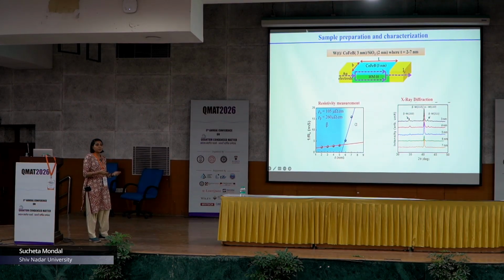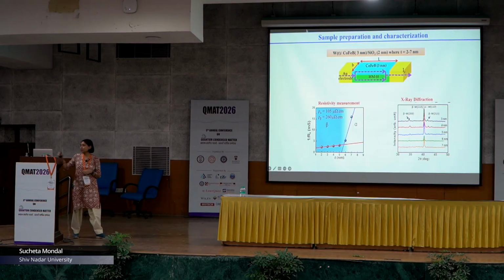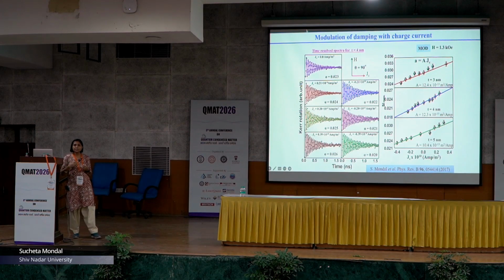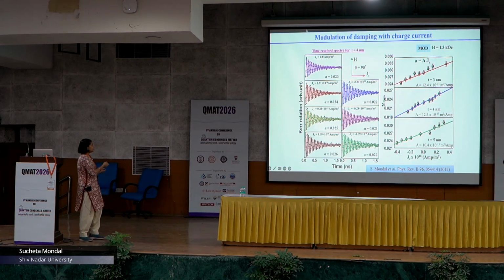There could be oxygen doping, there could be other changes. We have varied the thickness of the tungsten, and due to some chamber condition, we have achieved this phase transition from beta phase to alpha phase, which is from A15 to BCC in this thickness range. So we have verified those by characterizing them with electrical techniques and also X-ray diffraction to see the phase, and then we have performed the optical experiment.